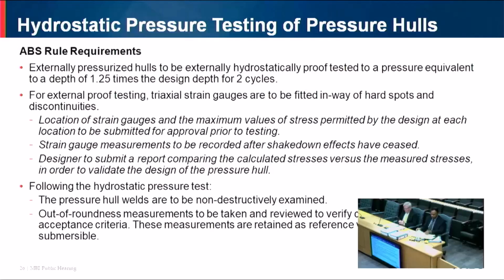So when it comes to hydrostatic pressure testing requirements for pressure hulls, what are the ABS rule requirements? Now these rule requirements are for metallic pressure hulls, okay? So the ABS rules require your pressure hull to be hydrostatically pressure tested to 1.25 times the design depth for 2 cycles, okay? And when you do this pressure testing, you have to strain gauge the pressure hull.